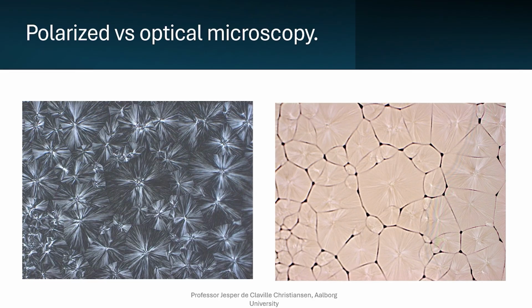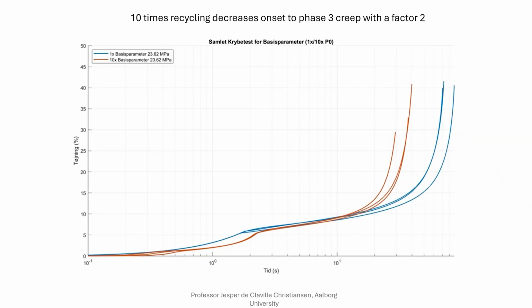So the morphology of the material changes when you recycle it, and it has some impacts. What you see on this slide is a creep test where we have strain on the second axis and time on the first axis. And what you can see is the blue line where you have the virgin material, and the orange-red lines where you have 10 times recycled material.